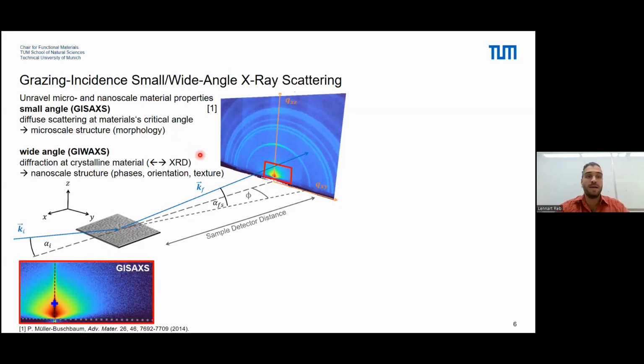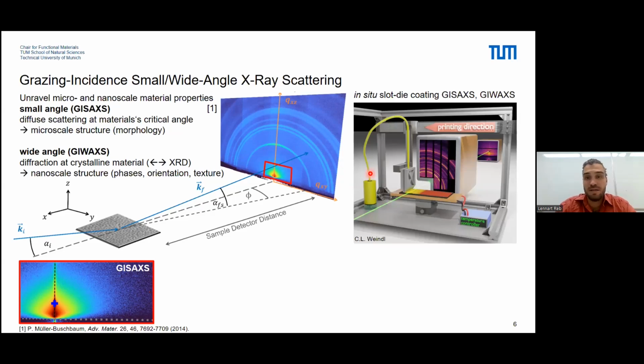Then we also have the wide angle X-ray scattering, which is kind of a complementary method to XRD. So the physical basis of this is similar to XRD, the diffraction at crystal lattices. What is different, however, is that with one single illumination shot, we can, as you can see here, collect multiple rings, where each ring is like a Scherrer ring, a polycrystalline sample that is probed, creating these different reflexes. So what we can access is not only phases, but also the orientation of phases, preferential orientation, which is texture. And these two experiments can be done at the same time.